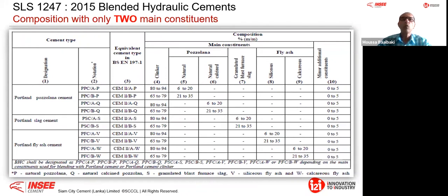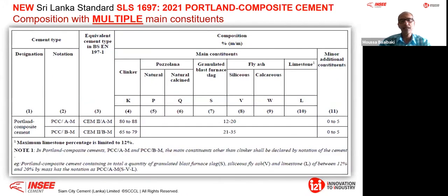But now, when you come to the new SLS 1697 Portland composite cement, you see the constituents are exactly the same. We have the clinker, the pozzolana, either natural or calcined, the slag, the fly ash, either siliceous or calcareous, and the limestone. Therefore, all constituents that are in the OPC, the Portland limestone cement, and the blended hydraulic cement are exactly the same in the Portland composite cement. But the difference here is that we have multiple main constituents.